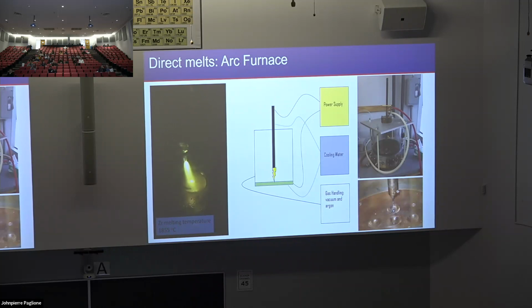There's one more thing that I want to show you here. When we cut off the plume, that flash was the dark shade changing. But the main point that I want to make here is you see how quickly this is cooling down. When you're in an arc furnace, you're potentially as high as 3,500 degrees C. And now this is cooled down below 600 degrees C in a matter of like 10 or 20 seconds. So you have absolutely no control over the heating and cooling profile. That's a limitation on this sort of growth.